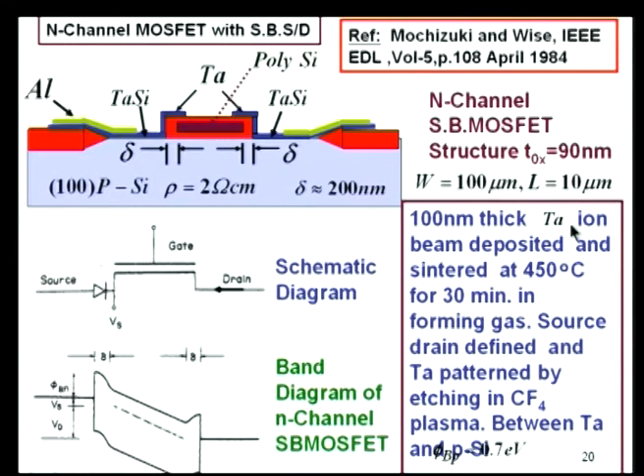100 nanometer thick tantalum ion beam deposited and sintered at 450 for 30 minutes in forming gas. Defined by etching to define this portion. After forming this gate region, polysilicon, exactly the same way as before, you open a contact, tantalum sputtered, annealed in forming gas. That forming gas annealing has slightly passivated those interface states. So, because of that, they could get some sort of MOSFET action.